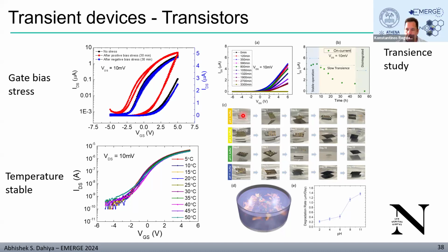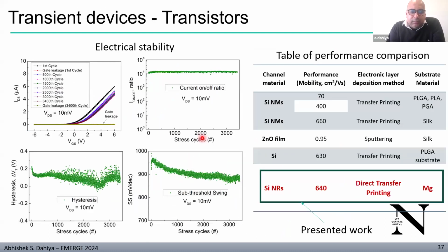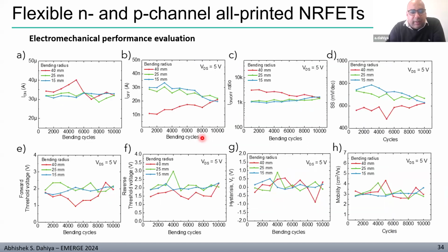Okay, another question about the durability and the reliability of printed transient electronic devices, and if you can overcome these issues to meet practical applications. Yeah, this is a problem, yes, and we are trying to characterize it, as you see, in depth, for example, here. If you have a conventional electrode, the problem may not be that much because the adhesion of the electrode is good onto the substrate compared to the printed one. So printed ones can have issues such as delamination of the electrodes or other layers.